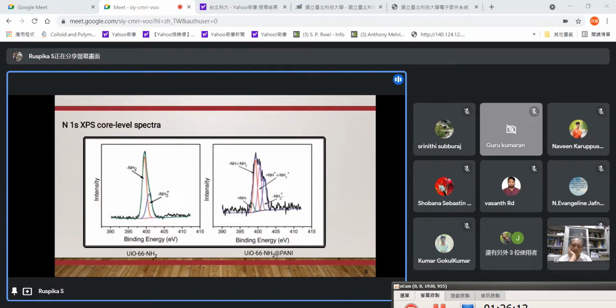And this is the XPS. In the nitrogen spectrum of UiO-66-NH2, the peak at 399.4 was assigned to NH2, and the other peak at 400.8 is due to the interaction between the amidogen and zirconium. The peaks at 399.3, 400.5, and 401.9 show the spectrum of UiO-66-NH2 at PANI, which corresponds to neutral imine-like and neutral amine-like nitrogen atoms, and protonated imine and protonated amine units.